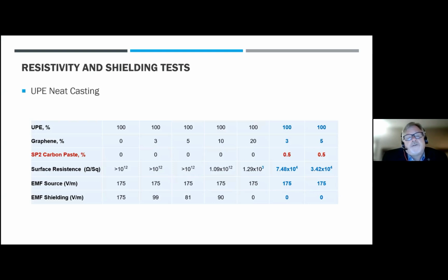But you can see the surface resistance in ohms per square is greater than 10 to the 12th, which is basically at the line where the equipment can read and measure the surface resistance. So essentially, you've got a lot of surface resistance there, right? So you're not getting conductivity, you're not getting any shielding. If you look at the second column, there's 3% graphene added, and you can see, again, not much conductivity, a lot of surface resistance. And you're starting to see some shielding, a little bit of dropping from that EMF source, from 175 down to 99.